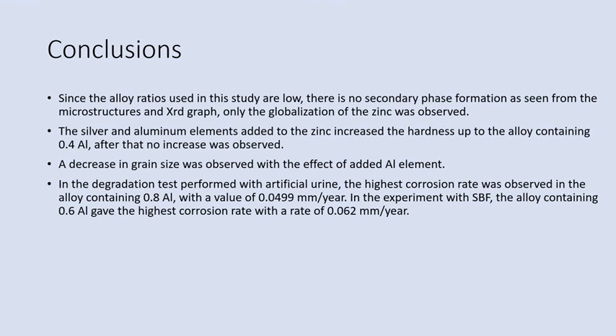In conclusion, we can say that the alloying amounts we use in this zinc alloy are low, and only globularization of zinc was observed, and there are no second phases. When it comes to hardness, we see that up until the point of 0.4 aluminium, there was an increase, but after that no increase was observed. We can say that aluminium has a grain refining effect, and when we add more aluminium to zinc, grain refinement was observed. In the degradation test carried out with artificial urine, 0.8 aluminium has the highest corrosion rate, and in the one carried out with synthetic body fluid, 0.6 aluminium has the highest corrosion rate.